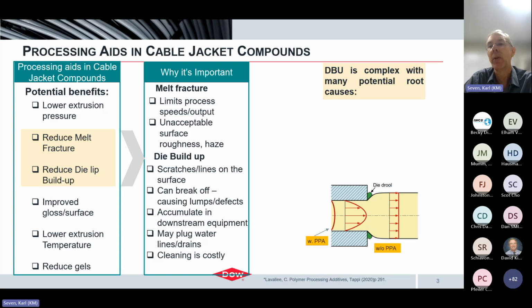So really the two most common reasons why these processing aids are used in terms of jacketing compounds are to reduce melt fracture and reduce die buildup. Melt fracture is basically flow instability that occurs within the die, and that can lead to unacceptable surface finish. Like I show here in this picture, as you go to higher and higher line speeds, this problem can occur more readily and become more severe,